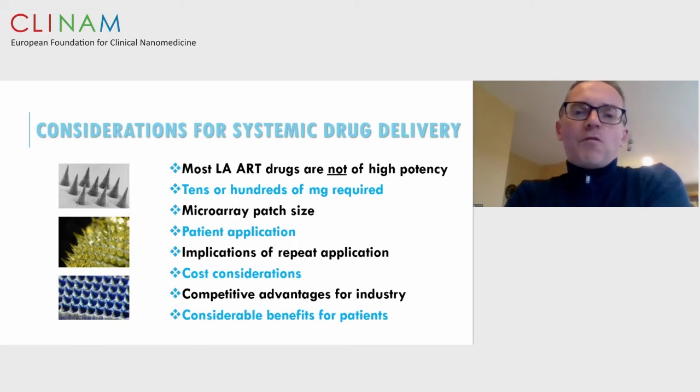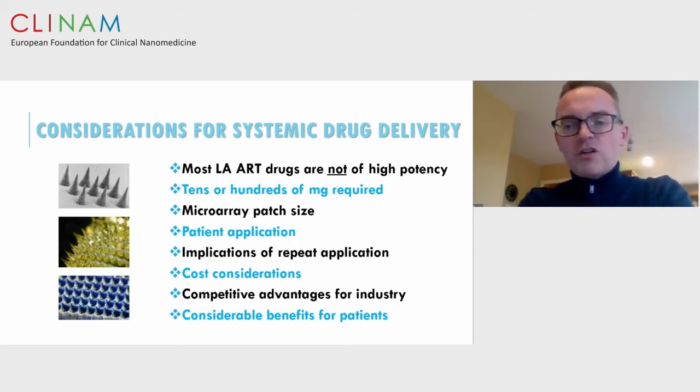What we need to think about, then, if we're going to deliver these drugs systemically using, for example, a microneedle system, is that most of these long-acting drugs aren't of high potency. We need tens or hundreds of milligrams to actually have a therapeutic or preventative effect. Now, bearing in mind that most microneedle patches were designed to deliver a few hundred micrograms, that clearly has implications for the patch size, and also for patient application. So as the patch becomes bigger, will people actually be able to apply those patches?